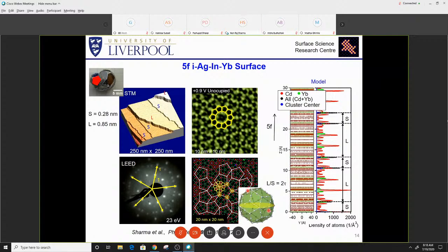The low energy electron diffraction comes from the long range order. With STM, we have the capability to resolve the structural motifs. So it is the dots of diffraction you see here that correspond. This was taken at positive bias. In any case, we have studied many quasicrystals, so we can make one single conclusion: the surface is bulk terminated and some systems relax.